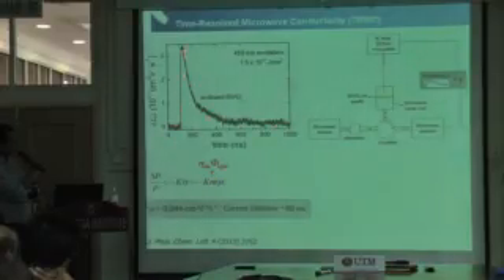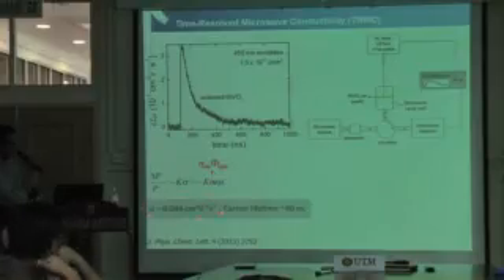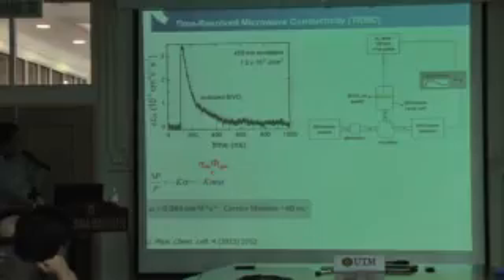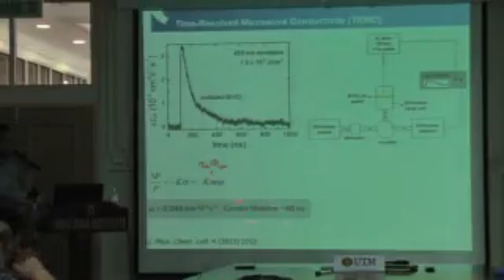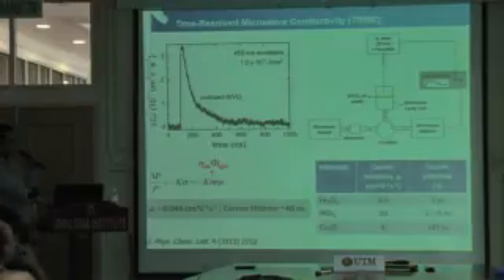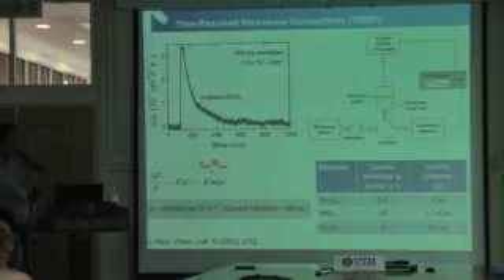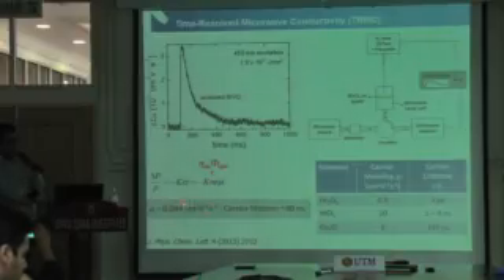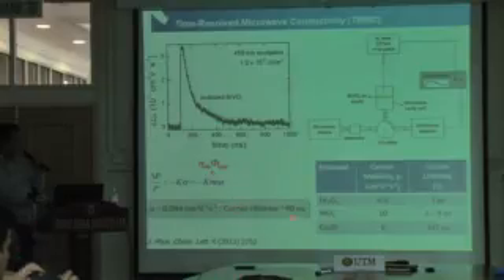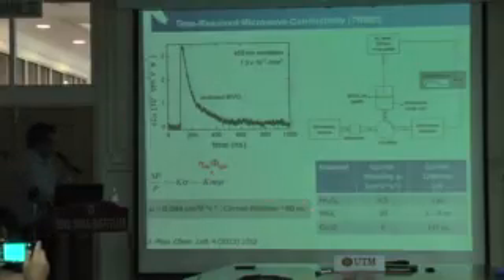So we did that. This is a typical plot of such a measurement. This is φΣμ, or basically you can take it as mobility as a function of time. And from the peak over here, we can get the mobility. This is done at different excitation energies. It turns out we get a mobility value of about 4 × 10⁻² centimeters squared per volt second for bismuth vanadate, and a carrier lifetime of 40 nanoseconds. If we compare this with other materials in the literature as photoanodes or photoelectrodes, we can see that the mobility is rather low. It is 2-3 orders of magnitude lower, but the carrier lifetime is actually rather long. So although the mobility is low, the carriers are pretty long-lived.